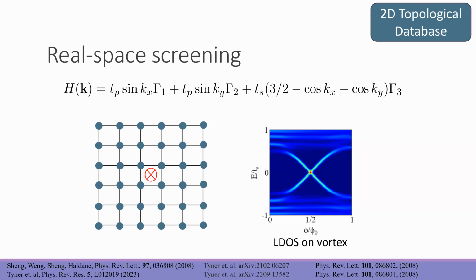But we have another way of probing this sort of bulk topology in this system, and that is in real space, which is kind of interesting. We can imagine taking some lattice; on the left here is the lattice in real space. And we can imagine threading a magnetic flux tube through the center of this lattice, that's the red X there. What was shown in these nice parallel PRL papers in 2008 was that if we thread this flux tube, it will bind a number of Kramers pairs given by our spin Chern number.